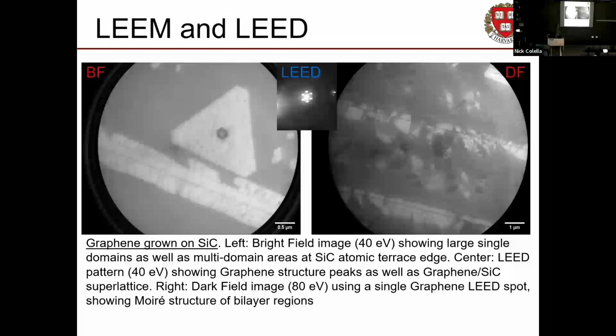And we get these dark field images like the one on your right, where some of the graphene is light and some of it's dark because some of it's oriented one direction, some of it's oriented the other direction. And there's actually even these fun little triangular structures which happen when you have 2 sheets of graphene on top of each other with some twisted angle in between them. You get this moiré effect. Really entertaining. That's the kind of picture you can take with LEEM.